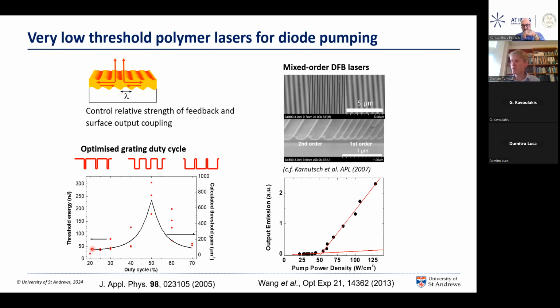Another approach, which was initially proposed by Lemmer's group in Karlsruhe, was to make structures called mixed order grating structures. You take a periodic structure and then you sandwich it between two other regions with half the period. In these very short period structures, you only get in-plane feedback and no surface emitting output coupling, so lower output loss. And then you control the amount of output loss by this second order grating region, where by changing the length of this overall grating section, you can control the amount of output coupling loss. And that can drive you down to a few tens of watts per square centimeter of light emission, with the light being emitted only from this region here, this sort of 5 micron long region of the device.